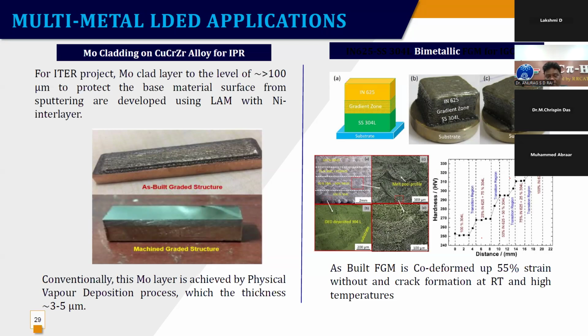Here the application can be different. Like once you go for co-deformation, you have one vessel made up of Inconel 625, and another part of SS 304, and you want to go for co-deformation, like you want to bend it or roll it. Then because of the different thermophysical properties and the spring back effect, things become very critical when you do such a forming process. So here also at the interface, we try to have a gradient, and you see on the right hand we have micro hardness shown, how the micro hardness is changing from SS to Inconel, a smooth change, and the microstructure is also visible here. So these applications are really good, and this we did for IGCAR.